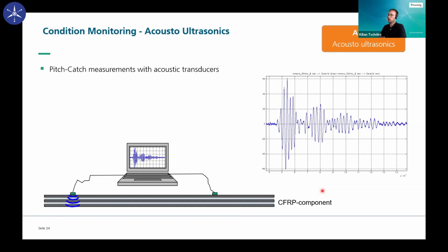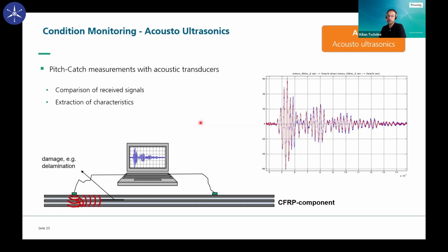In this figure here, let me show you the same idea. We have a CFRP component. We have a sensor system or a measurement system connected to transducers, and then the system excites a wave. This wave propagates in your structure and is collected by other transducers and stored in a database. If you have a damage in your structure, a delamination or a crack or fiber breakage, then the next measurement that you've started will show you again differences in the signals. And again, this can be used to analyze for the position and the type and in the best case also the size of your damage.